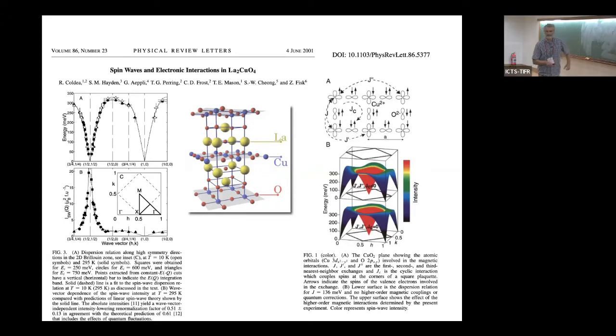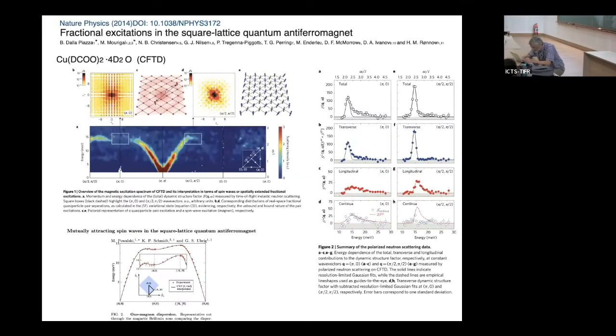And people did neutron scattering measurements. It measures the dispersion of the excitations of the underlying spin 1/2 antiferromagnet, and to be able to describe precisely the modes. What you see here is that this should be flat. In the very naive calculation, when we have only nearest neighbor exchange, this mode should be flat, but it is not flat. And then Radu Coldea and other people invoked the four-spin ring exchange to explain this behavior in the spectrum. So you really need to do some elaborate experiments to see this. What else is here? Okay, I think I will skip this.